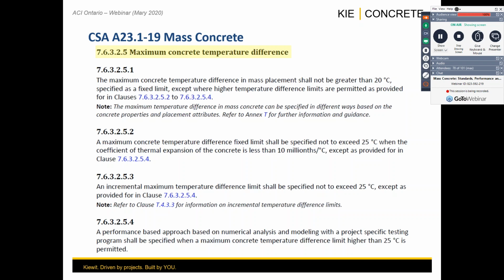The other one, under 7.6.3.2.5.3, is pretty much taking a concept of how concrete behaves, right? Concrete does not start from the first day already ready to tolerate the same thing as it can tolerate at 7 days. Concrete develops properties, and the resistance to thermal cracking increases as the properties develop. So it is the same approach in this case, and there are some agencies using it in North America, in the US and Canada, where they have an incremental approach. I'll show you an example. In that case, what you're doing is pretty much saying, okay, during the first 1 or 2 days, you're going to have this differential, and then after 1 or 2 days, you're going to have this other differential, and after 5 or 7 days, you're going to go ahead and use this higher differential.